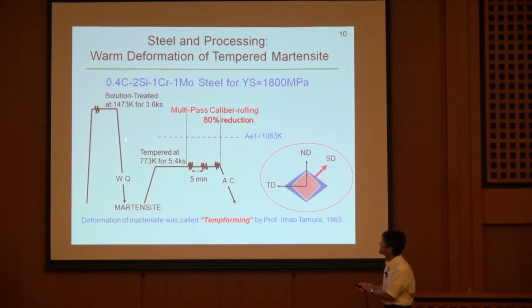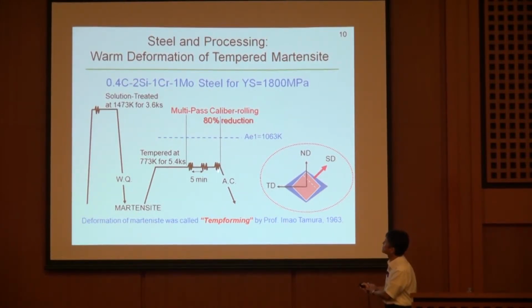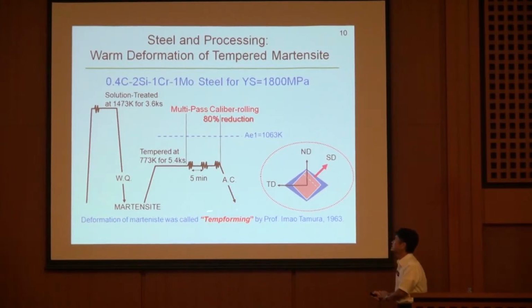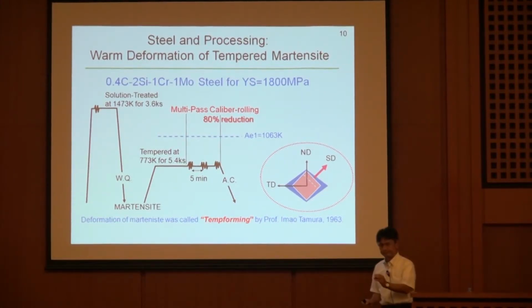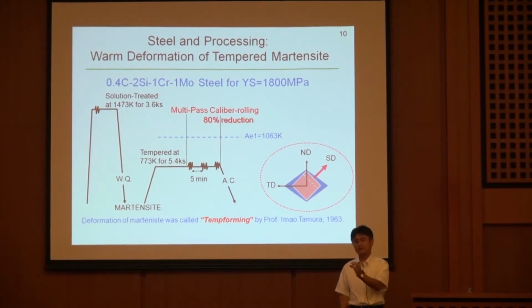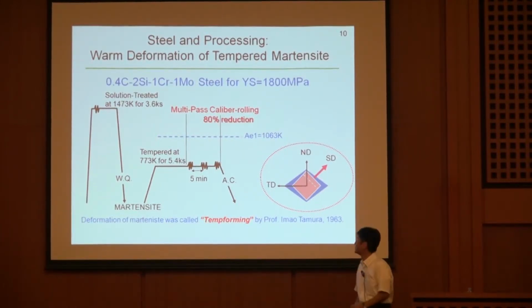And the process is rather simple. We did a quenching to produce a martensite, but martensite is too hard for deformation at ambient temperature. So then we heated it up to 500 degrees centigrade, where ferrite and cementite are stable phases. Actually, this is a tempered martensite, deformed at this temperature with a total 80% reduction. Then air cooled. With this process, we can get a bar sample with 2 centimeters square, like that.